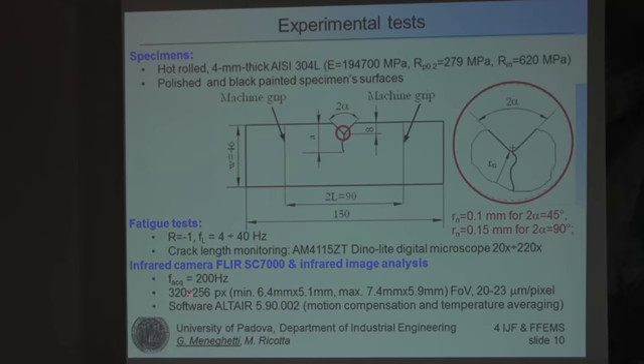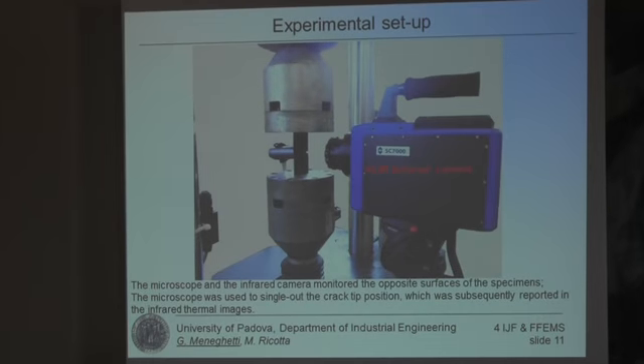The infrared camera operated at a frame acquisition of 200 Hz, and we achieved a resolution of about 20 micron per pixel using a spacer ring. And then we used the commercial software to analyze the videos taken from the laboratory. So this is the setup. We have the infrared camera looking at one specimen surface. On the opposite surface, we have the digital microscope. The digital microscope allowed us to monitor the crack population, to measure the crack length, and to single out the crack tip, so that we could report the crack tip from the digital microscope images to the infrared camera image.